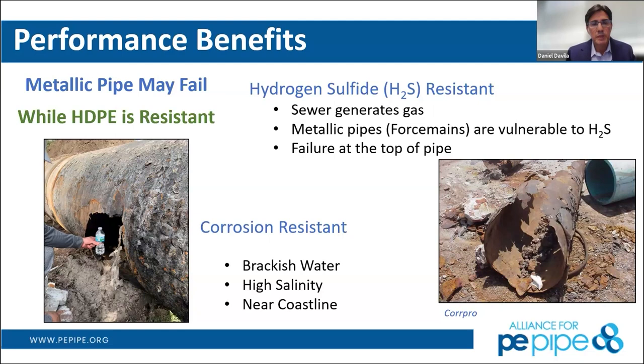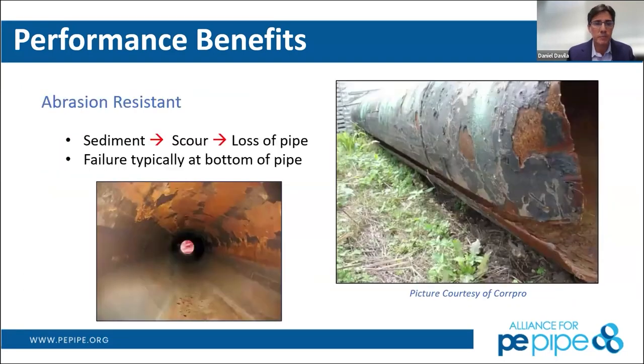This pipeline is resistant to hydrogen sulfide. Hydrogen sulfide is a gas generated by sewage, so it's very prevalent and present in sewage force main pipelines and usually stays at the top. So essentially on metallic pipes, what you will see is failure at the top, as you see on the picture to the right. And these are things that are avoided by using HDPE pipe because it's inert and doesn't interact with hydrogen sulfide. Similarly, it's corrosion resistant, especially when you're working near the coastline, brackish water or high salinity. We don't have to worry about that with HDPE being resistant. Next slide.